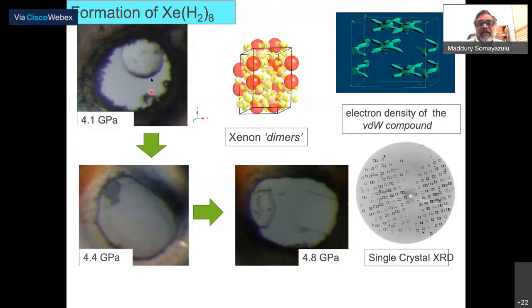At about 4 GPa, you see the formation of a crystal. And at about 4.5 GPa, we found that there was a phase separation and formation of two different kinds of phases. And with increasing pressure, you get different kinds of compounds and different compositions. I will not go into the gory details of all that, but this was one of the first measurements where we actually did single crystal diffraction, and we were able to get the electron density of this van der Waals compound and study the electron density as a function of pressure.